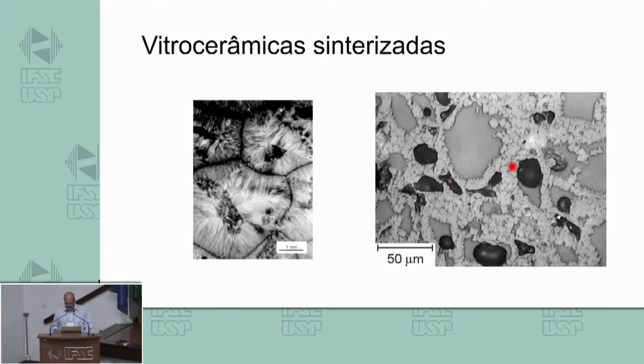And this is a sample of our research. It's a diopside glass crystallized from the surface. In the center of the particles, you see the residual glass. If you leave it in the furnace, the residual glass will decrease in amount, and you have more and more crystalline phase. But here you can see the pores that are appearing in the system, different kinds of pores. I'm going to tell you more.